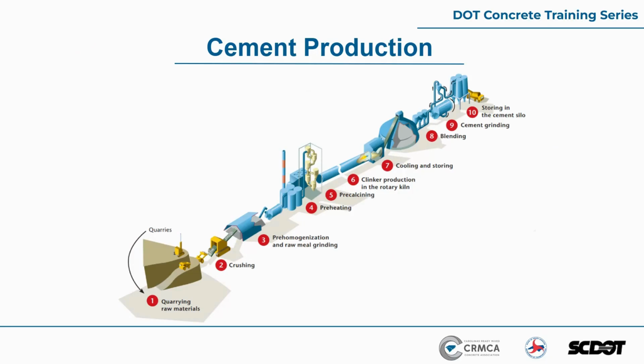From there, it moves to the preheating towers. Again, we want to get to that 2,700 degrees Fahrenheit, but we don't want to just wait till we get to our kiln to get there. So this material that sometimes is stored outside is then preheated and dried out before it gets to the precalcining tower. During the precalcining tower process, that uses the hot gases from the kiln, and it initiates the chemical reactions before those materials go into the clinker production in the rotary kiln. As it goes through the kiln, it is converted into almost the thought of a lava. At that point, the true clinker formation takes place as far as the chemistry.